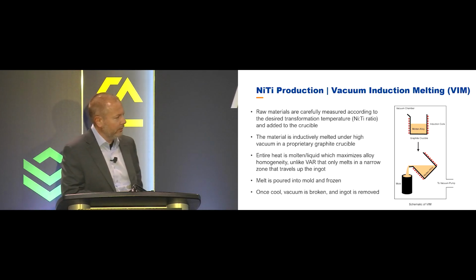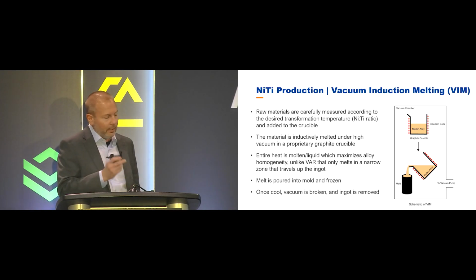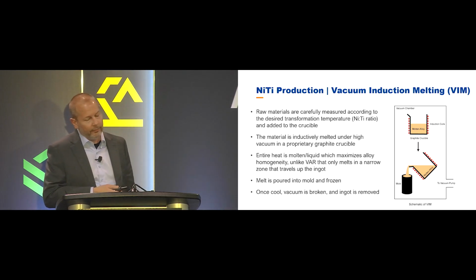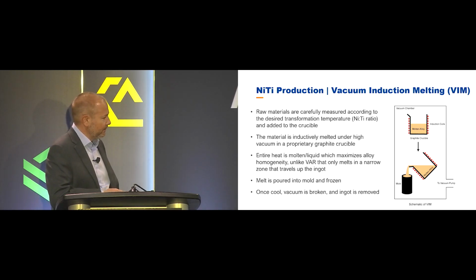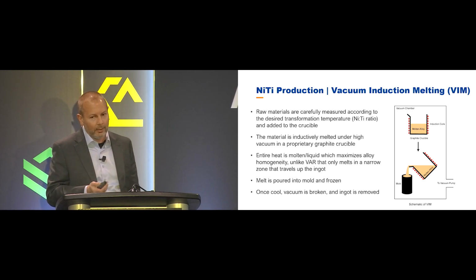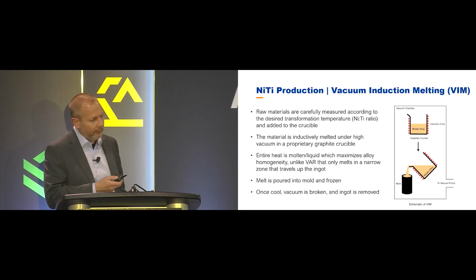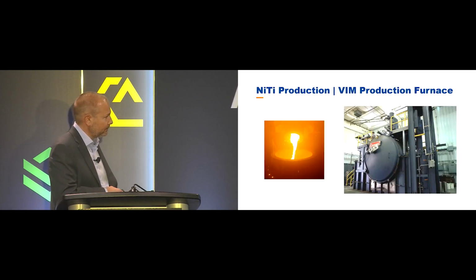Once it's fully molten, we're happy. We hit a timer, we hold the material, we'll pour it off in a mold, and it freezes. So it takes about an hour from power on to power off to melt around 420 pounds of nitinol.